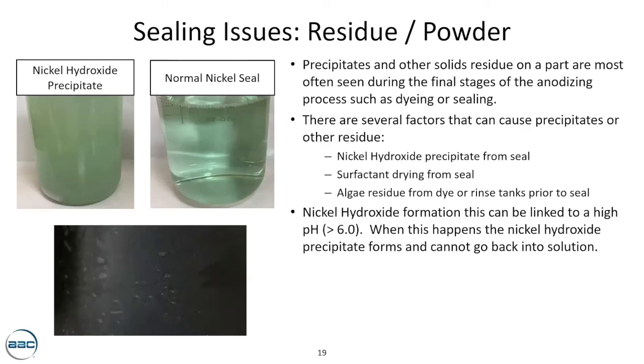Residue and powder. Precipitates and other solid residues are usually visible at the end of the anodizing process, usually during the dyeing and sealing processes. There are several factors that can cause precipitates to occur. One of them is nickel hydroxide precipitate formation, surfactant drying from the seal, or algae residue from dye or rinse tanks. The nickel hydroxide formation is usually linked with higher pH. If the pH of a seal goes above 6, the nickel hydroxide precipitates and cannot go back into solution. You can see in the picture how a nickel hydroxide precipitate looks, and on the right you can see how a normal nickel seal looks.